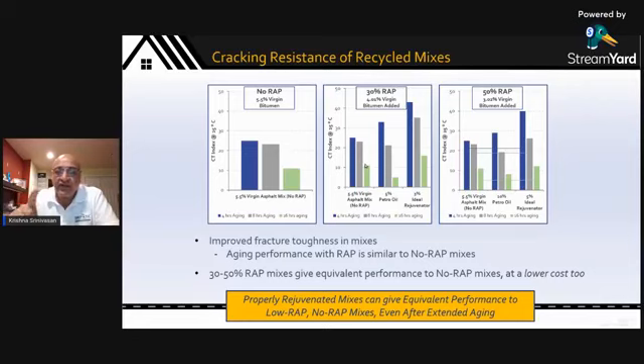It's not only important that you get the properties of the mix today, as made in your lab or as put down in the field, but over the course of time you want to achieve properties that are equivalent to no RAP mixes. And that is what a good rejuvenation technology will allow you to do, which is make you impervious to whether you're using RAP in your mix or not. You should be able to generate performance out of it, both instantaneous and long-term, that is comparable to no RAP mixes.